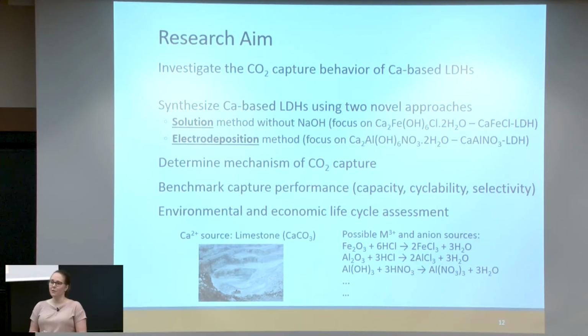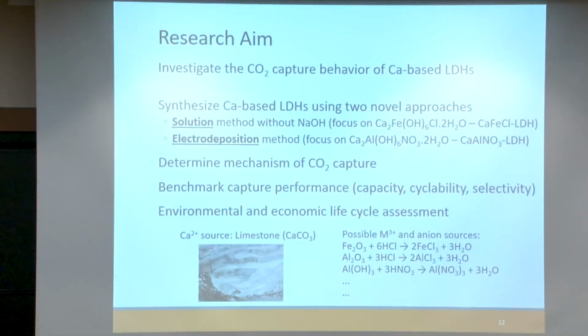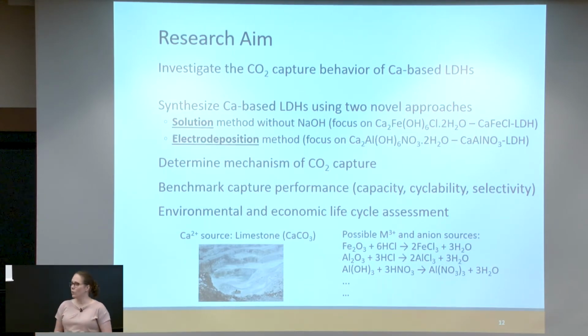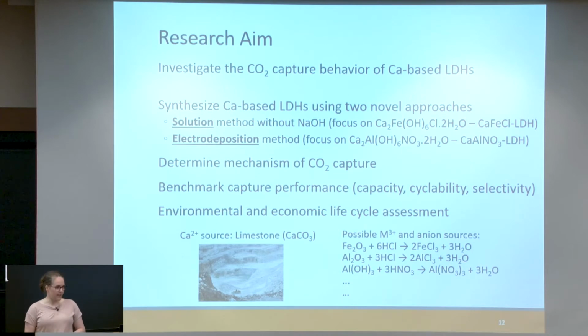It's very important to keep in mind, if we're synthesizing these materials, what are the starting ingredients that we need to use? And so what you will see here is calcium source limestone, which already has CO2 in it, right? It's a carbonate mineral. So what really comes into play here is if we can get really good cyclability of this material, then that will help offset the fact that when we make it in the first place, we're emitting CO2. Then the other thing to keep in mind is what are the other ingredients that need to be used and where can we get them from? So for example, ores, iron ore, alumina, so aluminium oxide, for example. So this will all go into the life cycle assessment side of the analysis.